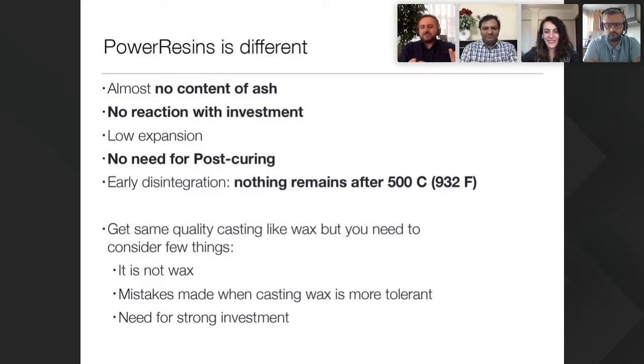Wax casting and resin casting are different. When you cast resin, I would strongly recommend being more careful on the process, like the mixing, because wax melts at 80 degrees. Whether you put a bit more or less water, or mix a bit more or less, won't affect your final casting much. But with resin, because the resin remains in the investment and disappears between 300 to 450 degrees, it's important that you do it properly and try to get a stronger investment. Okay, that's good for the question.